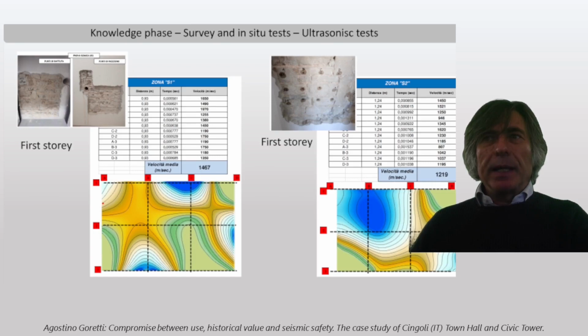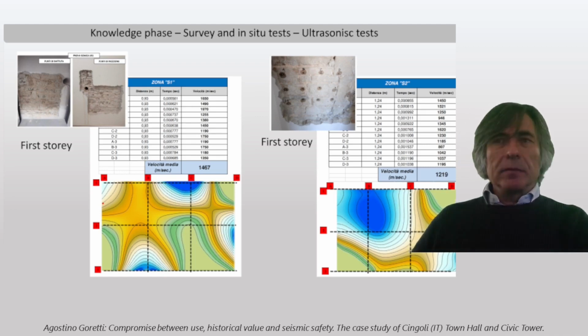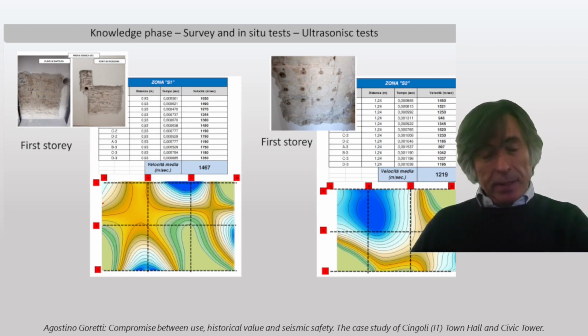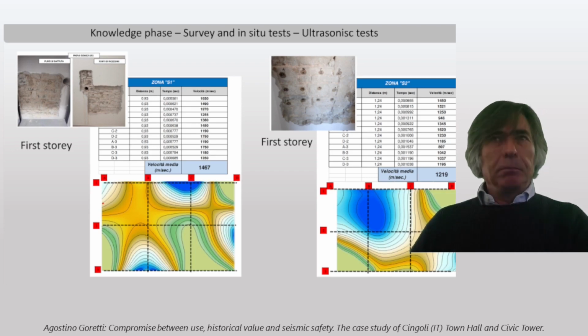And this is also confirmed by the ultrasonic test. You mount the receiver on one side of the wall, you make the input on the other side, you measure the time lag of the arrival time of the pulse, and then based on the distance you measure the velocity of the waves, and in this case the velocity of the waves was in the order of 1200 to 1400 meters per second. This is an average low value, meaning that in any case there are no significant voids in the masonry. It's almost homogeneous masonry. It's not a bad value, I would say. So again, it's a proof about the homogeneity of the body.